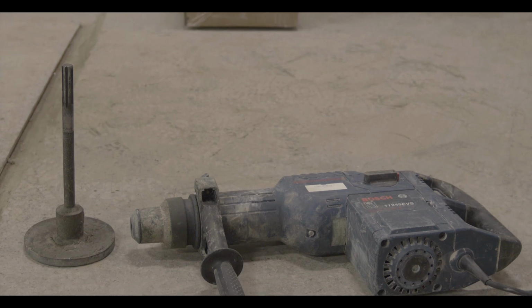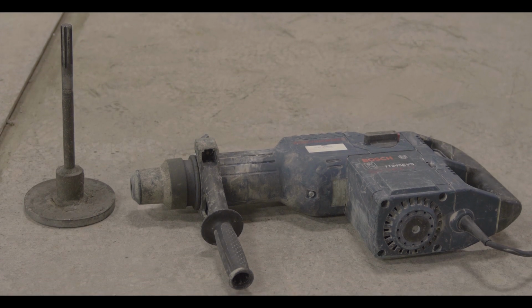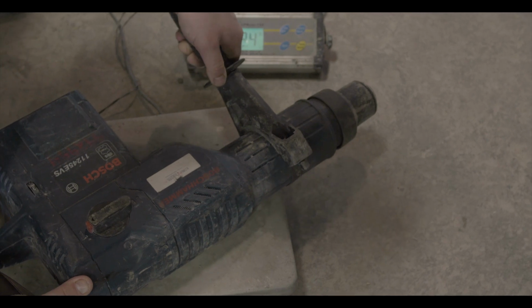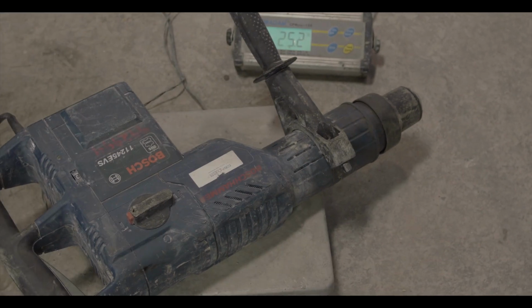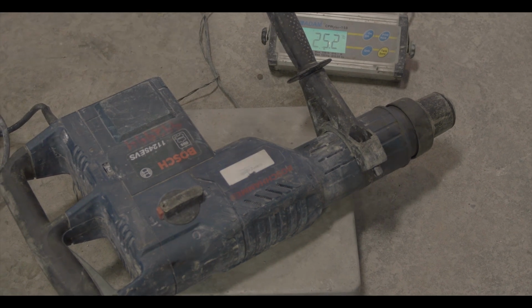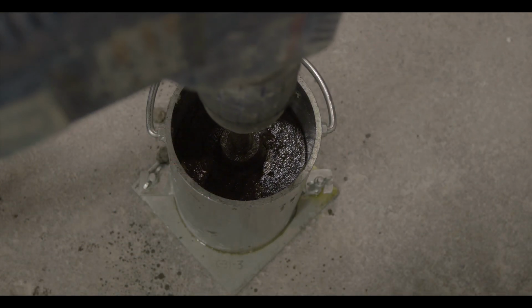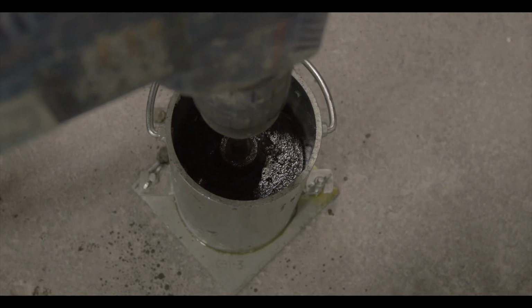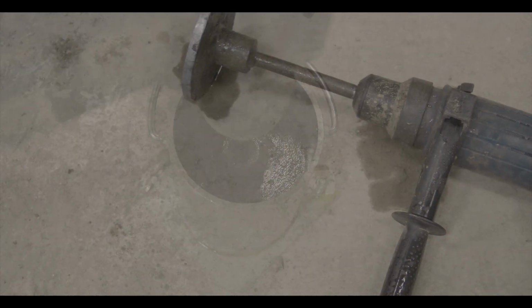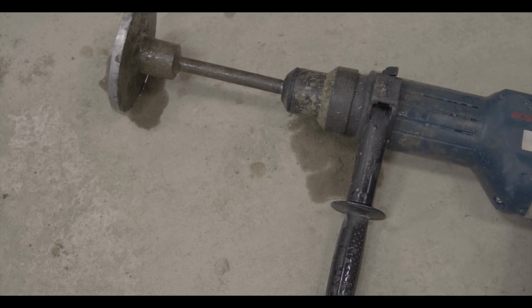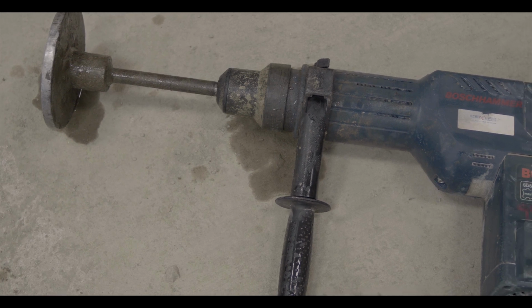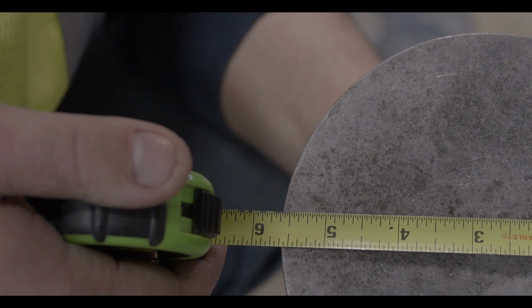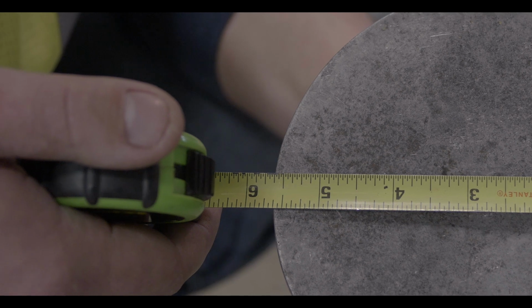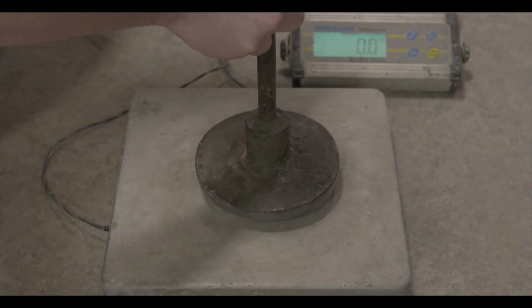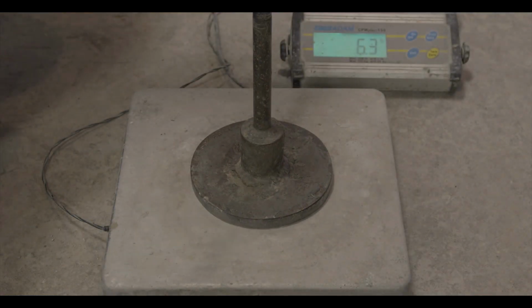A vibrating compaction hammer having a mass without tamping plate and shaft of 22 plus or minus 3.3 pounds. It also shall have a minimum power input of 900 watts and be capable of providing 2,000 plus or minus 200 impacts per minute. A circular steel plate attached to a steel shaft, which is inserted into the vibrating hammer chuck. The plate diameter shall be 5.5 inches plus or minus 1/8 inch, and the mass of the plate and shaft assembly shall be 6.6 plus or minus 2.2 pounds.